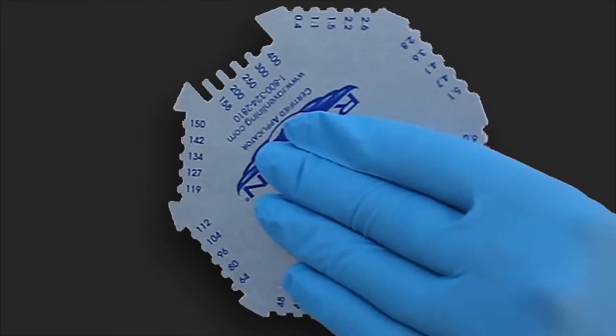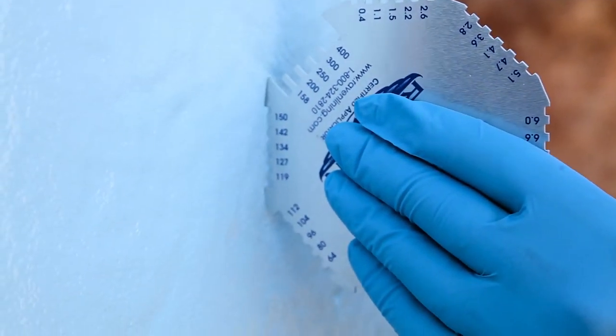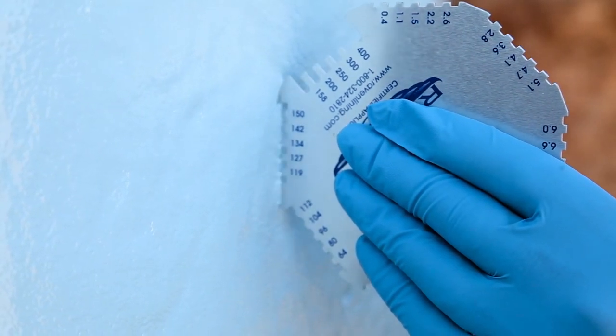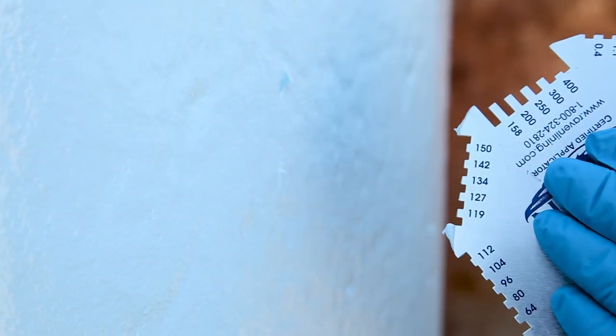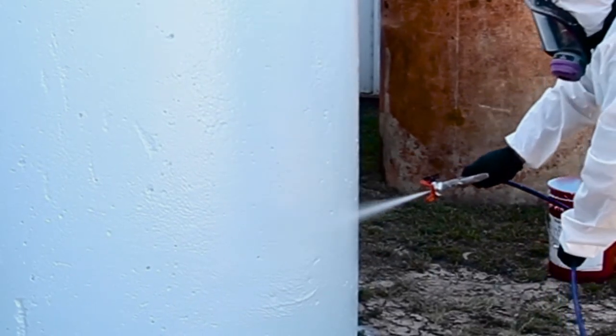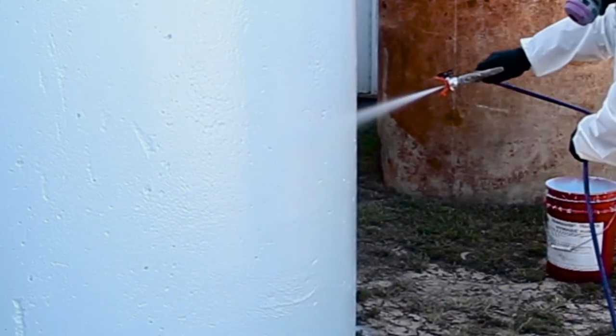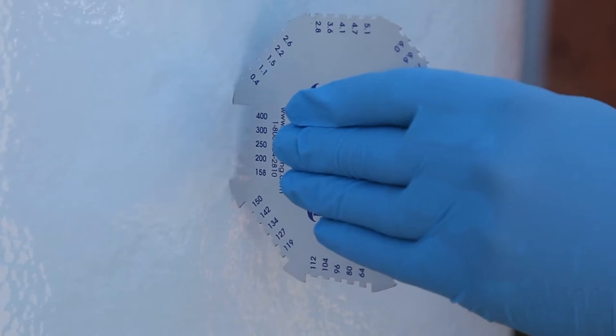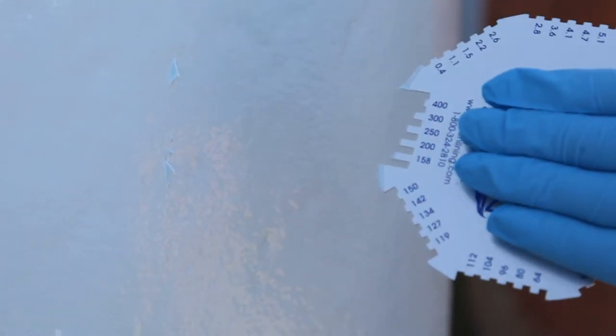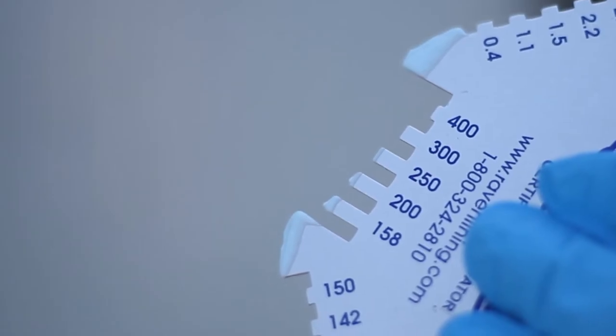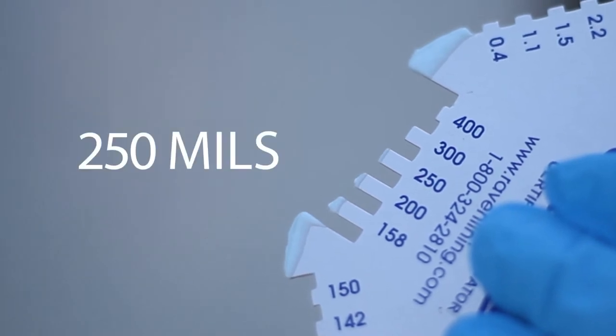To properly measure the thickness of the coating, locate the tab that matches the required thickness. Carefully place the gauge until it is in full contact with the coated surface. Remove the gauge in the same manner. This is the wet film thickness known as mils. The gauge shows 127. We sprayed again to meet our required mil thickness. This time we are just under 250, and as you can see, we coated to our goal of 250 mils.